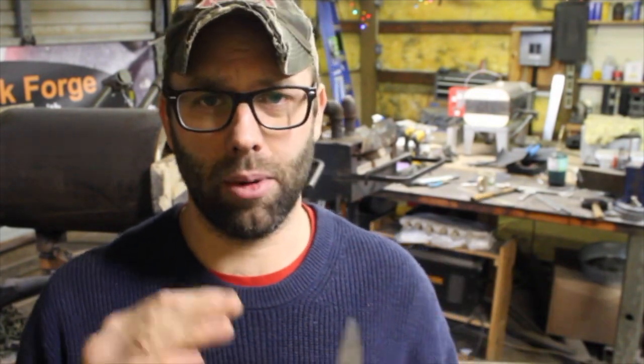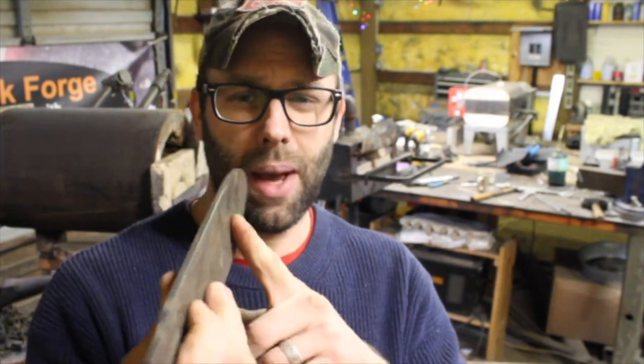Another common solution is to apply some careful heat to portions of the blade and straighten it out. This is not something you can just do with a Damascus blade like you can with a monosteel blade, because adding heat to it is going to temper parts of it out differently, and that's going to affect to some degree the final etch of the blade, so I don't want to use that method. Also, in this case, the spine of the blade is quite straight and the only warpage is down here where it's thinner. You might say, why not just leave your blade thick enough to grind off any warpage issue and just correct it that way?